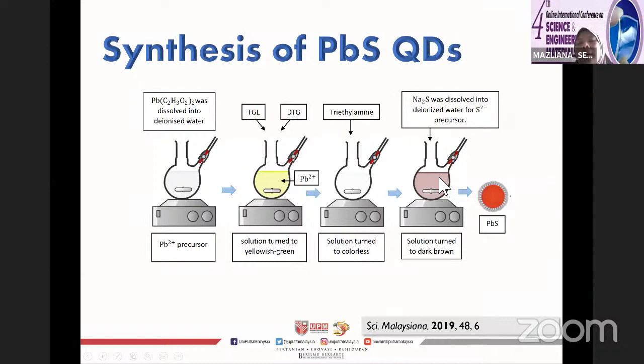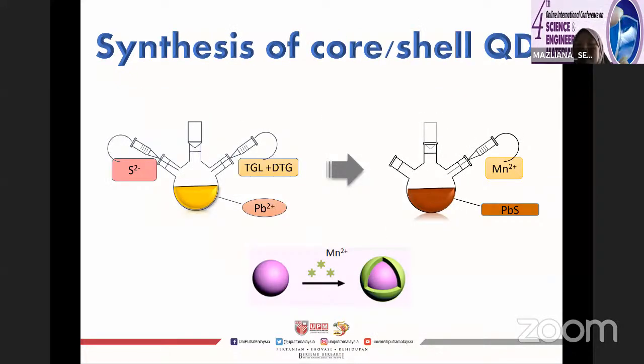So here, when I mix the lead and sulfur precursor solutions, I control the molar ratio to 1 to 0.3. If you would like to synthesize bare core quantum dots with different sizes, you can change the molar ratio, because from my experience, when I increase the ratio of the sulfur, it increases the size of the quantum dots.